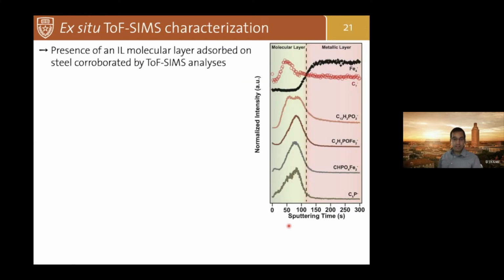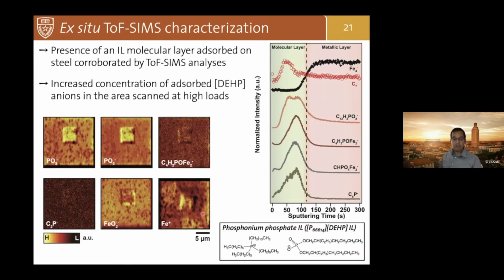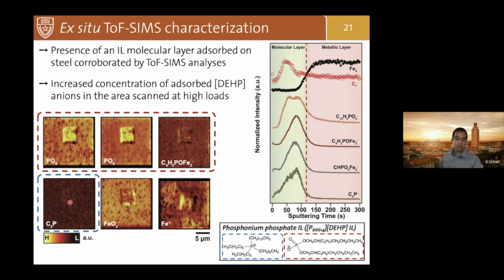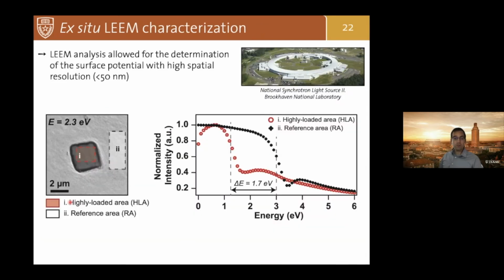Being surface analysis people, we were also interested to look at the molecular fragments in these boundary layers. And what we show is that in the region stressed at very high loads, we have an enrichment of the anion, the phosphate, while we don't have an enrichment of the cations, a small enrichment probably. So all these changes were also correlated to changes in surface potential that we measure by low energy electron microscopy.